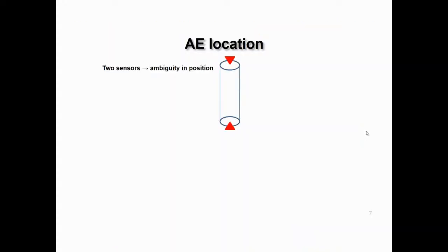We've done some work on the locations as well. We've got a big problem in that we've only got 2 sensors on the top and the bottom of this sample, but we can still do quite a lot with that. We can't put sensors on the side because then we wouldn't see the resolution that we need with the CT images. We couldn't get X-rays in as easily. So we really have to have X-ray transparent cell walls.